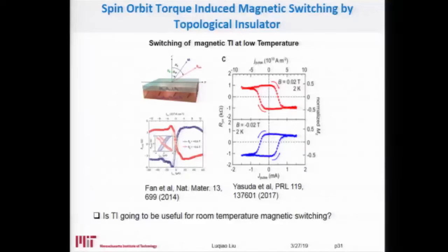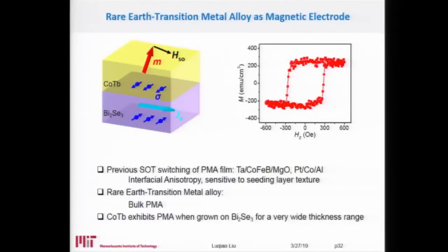So that's our goal. We try to integrate the zero moment or low moment magnets that we developed earlier, like cobalt-terbium alloy, with the topological insulator, bismuth selenide. The bismuth selenide is grown by MBE at Penn State. They ship the sample to our lab, we remove the capping on top of the topological insulator, and then put down the cobalt-terbium alloy. We can verify that the cobalt-terbium growing on top of bismuth selenide still has relatively low magnetic moment, although it's not completely compensated. It's a low moment, and it has a perpendicular anisotropy, which is preferred.